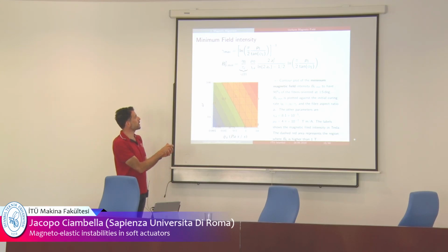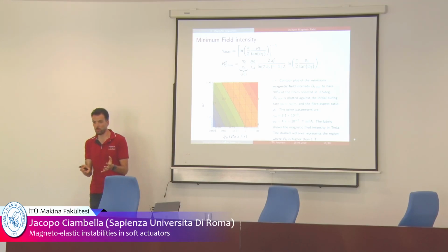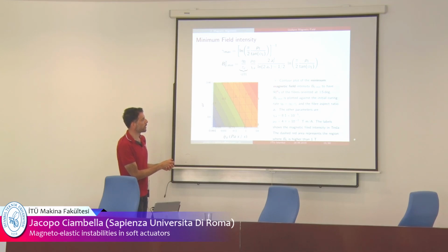So these quantities here only depend on the matrix. This depends on the magnetic properties of the particles, and these others are only related to the geometric properties of the particles. Okay? This equation gives you the minimum field you have to apply to obtain a certain orientation. Let's say, for instance, that you want 90% of particles to be oriented with the field within plus minus 5 degrees. This equation gives you the minimum field you have to apply for a given matrix and for a given aspect ratio of the particle.